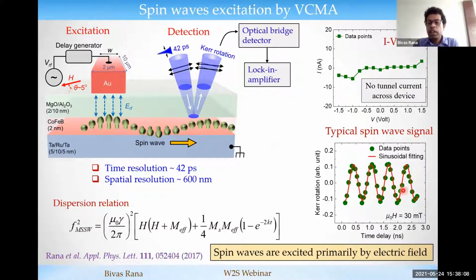And here are the typical spin wave signals. To measure the spin wave signal, we vary the delay of the laser pulse with respect to the RF current by using an electronic delay generator. The spin wave signal varies sinusoidally as a function of this delay time. By fitting with a sinusoidal function, we can extract the spin wave amplitude, which is proportional to half of the peak-to-peak value.